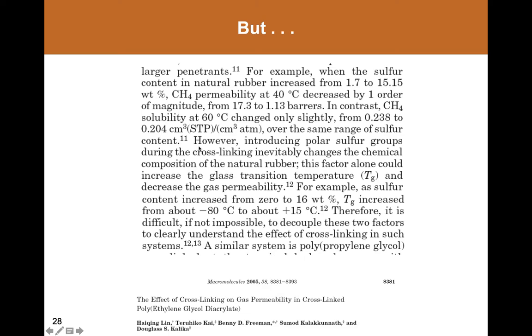And the issue is that in the case we saw on the previous slide, that is with natural rubber, as the sulfur content increases, the glass transition temperature goes up by close to 100 degrees C. This is the phenomenon that Goodyear was basically after by making the natural rubber, turning it from a soft, gooey material into a hard rubber. Accompanying that transition in mechanical properties was an enormous transition in glass transition temperature. And you could imagine that as the glass transition temperature went up this much, that would readily accompany a decrease in chain motion and a decrease in diffusion coefficients and therefore permeability.